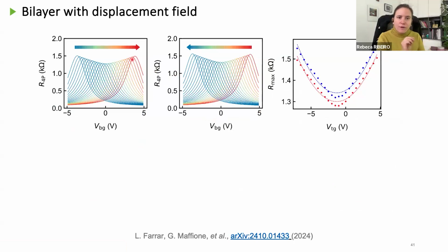This time I'm gonna follow that minimum, but at room temperature, okay? So what I'm gonna do inside my AFM is I'm gonna fix an angle, and I'm gonna measure my resistance as a function of the gate going in one direction and in the other direction. So these are different values of the top gate that start here and go up to here, and then it goes from here to here. If I follow these points, the maximum of the charge neutrality point, I'm gonna see two parabolas, one moving in one direction and the other one moving in the other direction. And there is a minimum for both of them. And that minimum is, as I told you before, where the energy gap fully closes, okay?